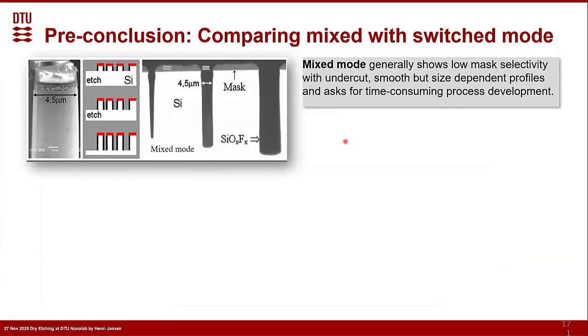Now, okay, we did it with fluorocarbon, and we saw the pros and also maybe some cons. And now let's go back to the original one. There was the mix process with oxygen. It showed, let's say, a low mask selectivity, because everything is supplied all the time at the same time, with some undercut at the top. It also has really time-consuming process development, because the profile is changing from positive into negative. But when you're using solely oxygen as the inhibitor, there's not that much process drift, and it is very tool friendly.